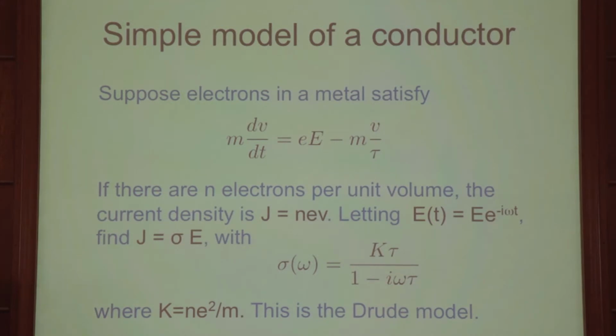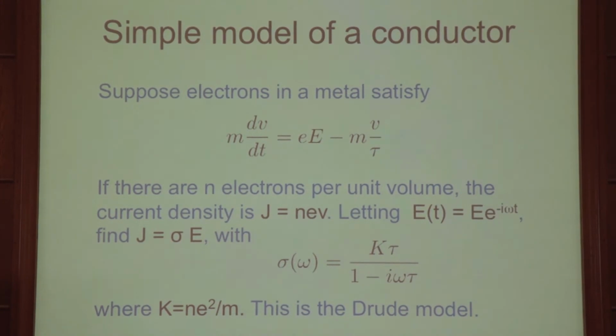If you apply an oscillating electric field, e to the minus i omega t, you can solve this equation for v, compute the current J, and then using J equals sigma E, compute the conductivity. And what you find is this formula, where the conductivity is a function of omega. It goes like a constant k times this relaxation time tau, divided by 1 minus i omega tau, where k is essentially the number density of electrons times e squared over m. And this is called the Drude model, a model of a conductor first proposed in the early parts of the 20th century.